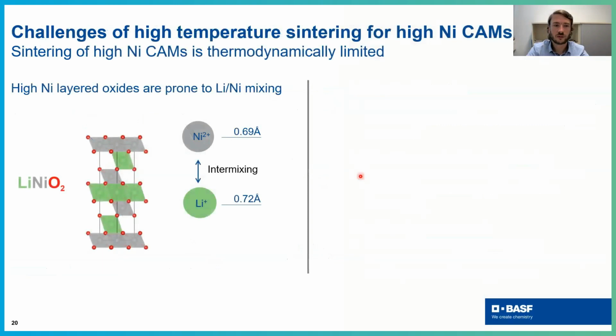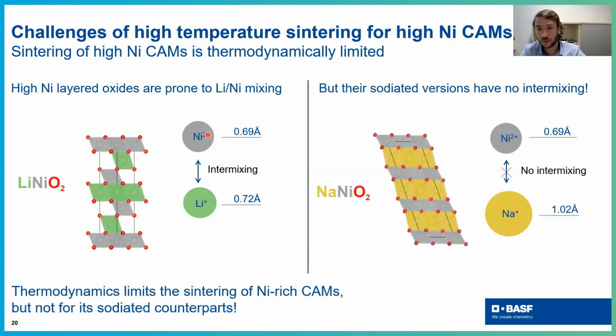So the idea of a study conducted here at BELLA was to make a perfect, or as perfect as possible, lithium nickel oxide, which is single crystal and which has the lowest lithium-nickel exchange possible. And this is very tough, because especially for lithium nickel oxide, you always have the problem that nickel goes into lithium sites during the synthesis, just because they have similar ionic radius. So the idea was to start with something where you do not have such a problem. And this is the idea of Leonard Kager and Daniel Weber.